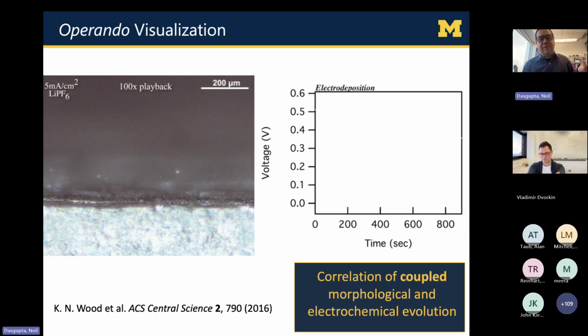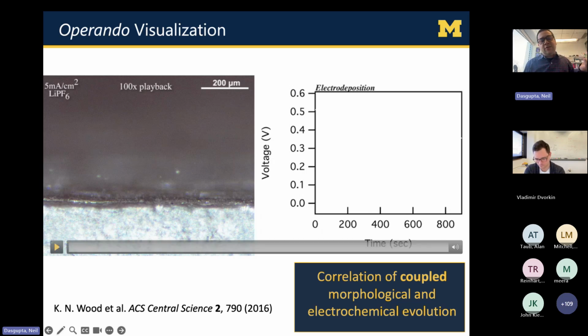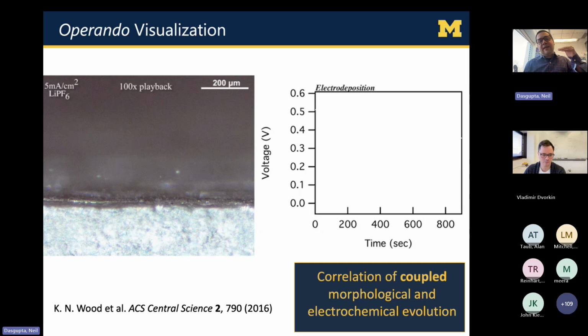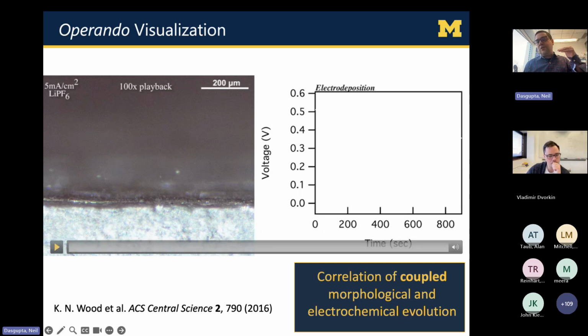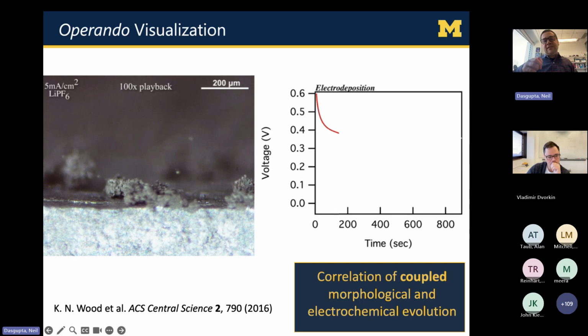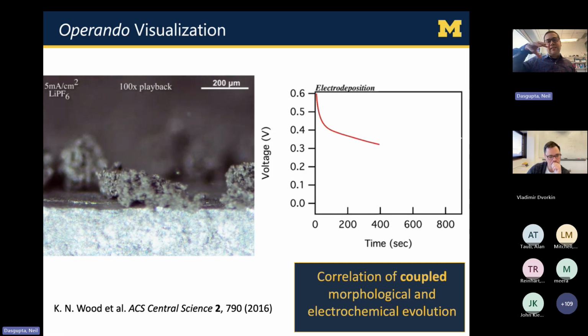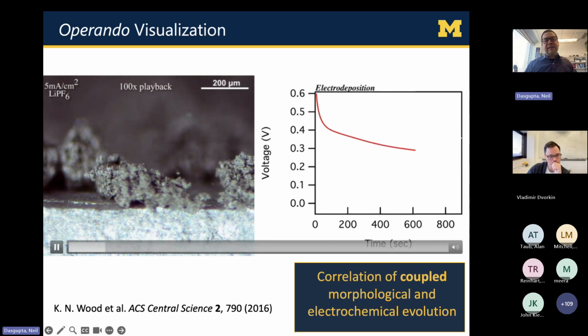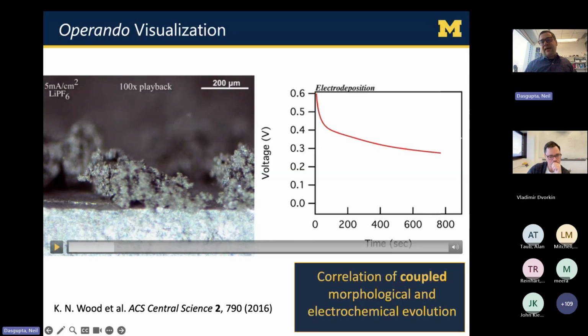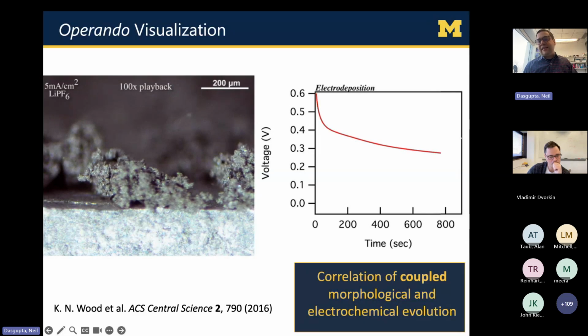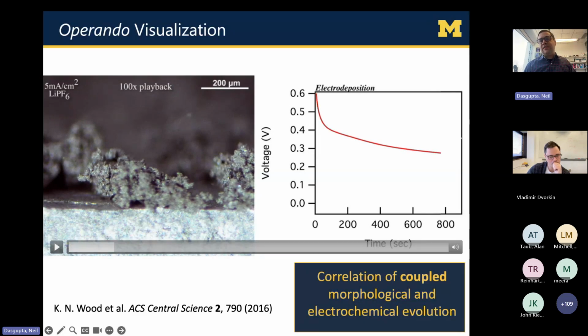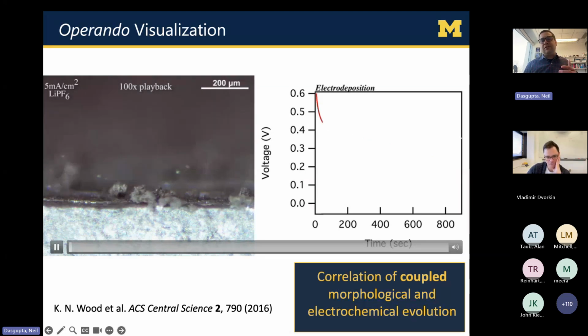Let me show an early example of that. This is a paper that's almost 10 years old now from my group, where we first introduced this concept of visualizing what's happening inside the battery and synchronizing it with the voltage. On the left, you're seeing a lithium metal anode inside a battery, and on the right, voltage versus time. As I play the video, you can see we're able to observe these dendrites, these non-planar, non-ideal plated lithium geometries that are evolving in time. On the right-hand side, we synchronize that with the voltage trace of the material. This allows us to understand the origins of some of these electrochemical signatures.